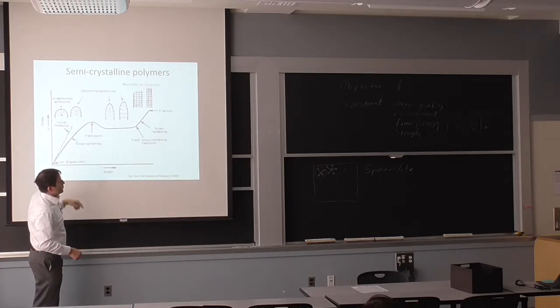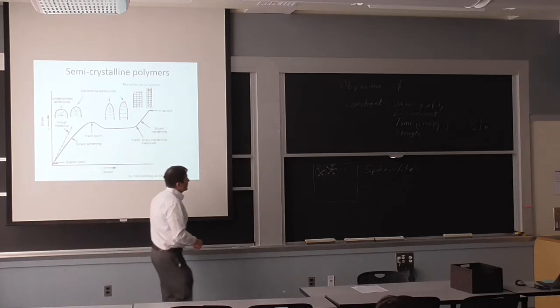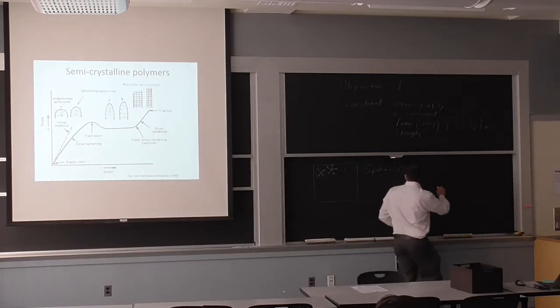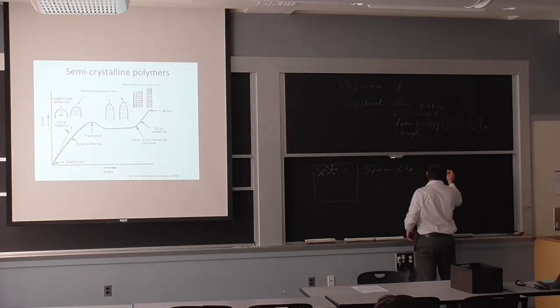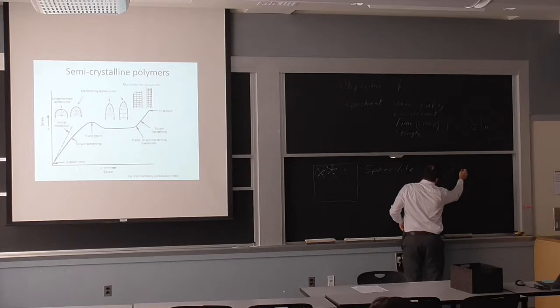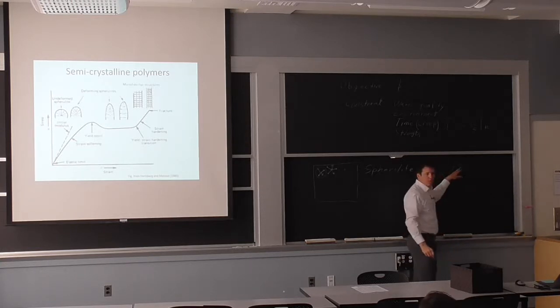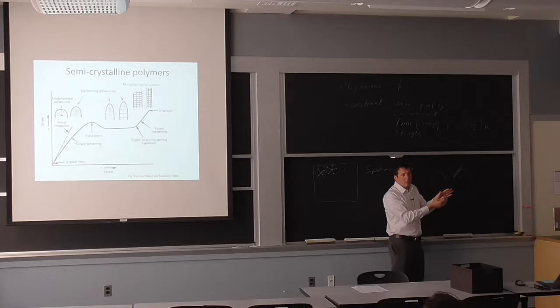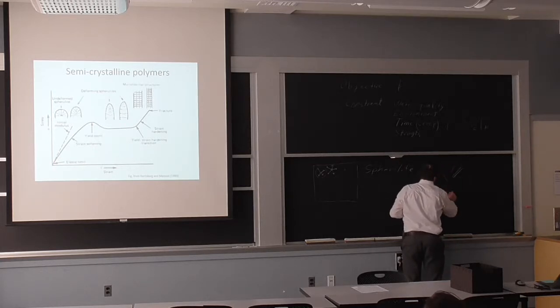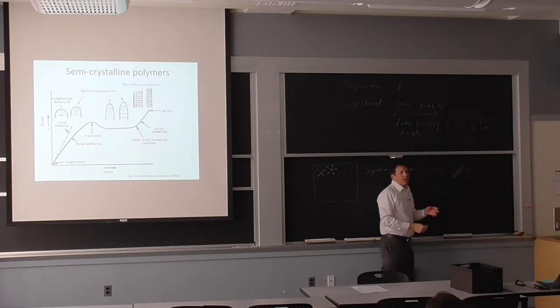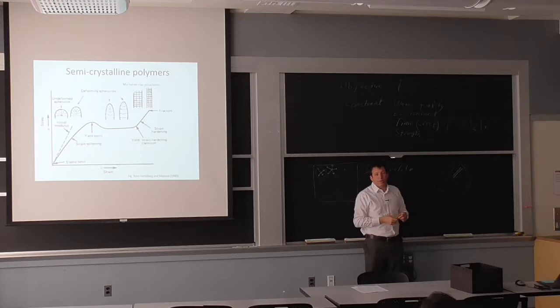all rounded arrangement. What happens with the rounded arrangement, it doesn't really show here. So if I'm round like this, and then I got crystallite oriented in different directions, but if I'm looking at 45 degrees here, I can have 2 crystals. So this is very strong. This is very strong. But in between I have the amorphous material. It's very easy to shear. So if I'm looking at this structure, this is where the permanent or the flow deformation is going to start, because I have that special orientation to allow for it.